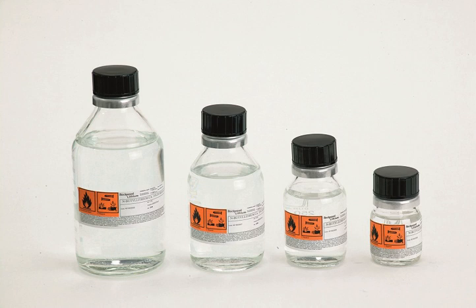For example, TMEDA increases rates and efficiencies in many reactions involving organolithium reagents. Toward alkyllithium reagents, TMEDA functions as a donor ligand, reduces the degree of aggregation, and increases the nucleophilicity of these species. However, TMEDA does not always function as a donor ligand to lithium cation, especially in the presence of anionic oxygen and nitrogen centers. For example, it only weakly interacts with LDA and LiHMDS even in hydrocarbon solvents with no